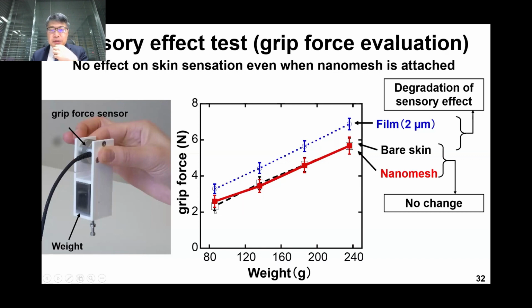The black dashed line is the data of bare skin, and the blue dashed line is obtained when the fingertip is covered by 2-micron thick ultra-thin film. So even though such thin film attachment may cause a slight increase of minimum grip force, the nanomesh attachment shows almost identical grip force with bare skin data. So in that way, we prove there is no effect on skin sensation when nanomesh is attached.